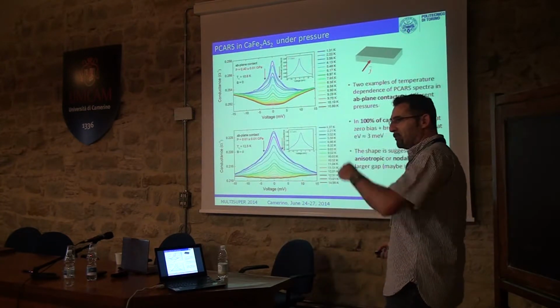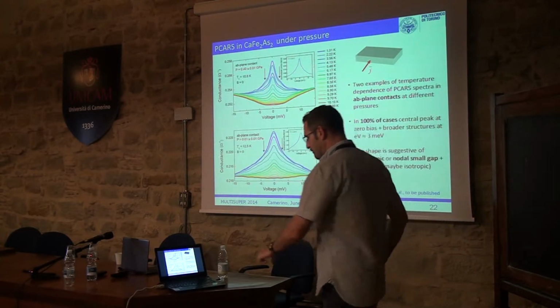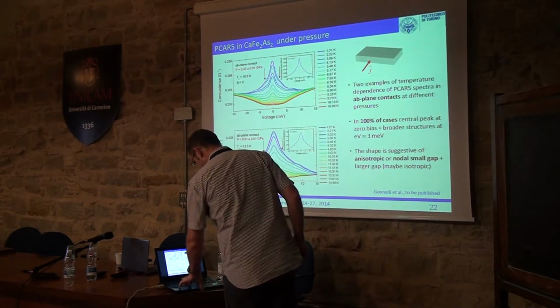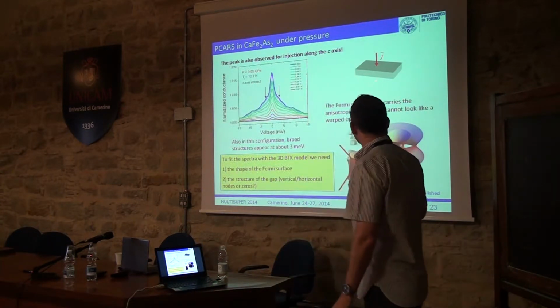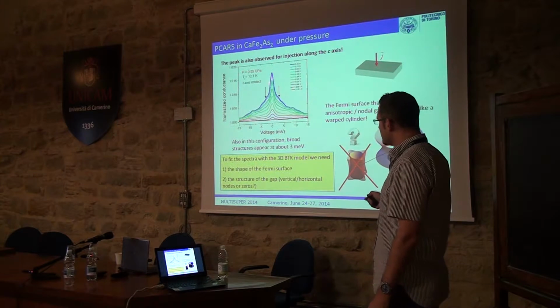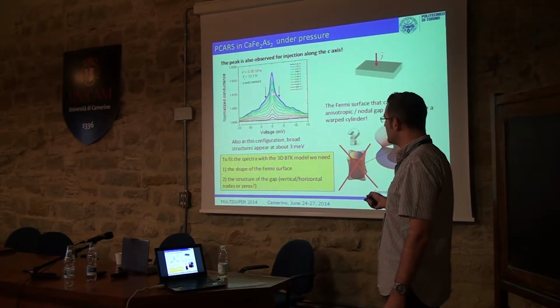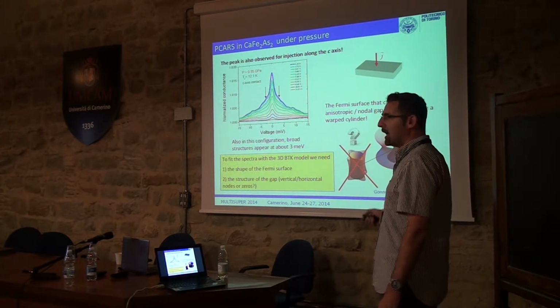But what happens if we inject the current along the c-axis? Because this is the final test. If we inject the current along the c-axis, we still see the same structure, the zero bias maximum plus additional structures.